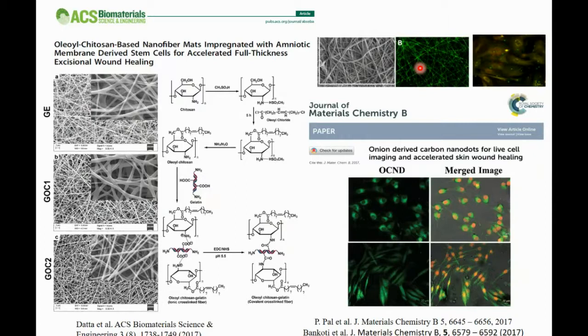And these carbon dots were explored for live cell imaging. So we could see that we can track these cells using these carbon dots: onion peel based carbon dots, green chili derived carbon dots, whey protein derived carbon dots. And these carbon dots were able to track the cells up to 8 generations. However, it doesn't have any bleaching effect. It is not toxic apparently. Okay, so therefore this can be wonderfully used for this kind of application.